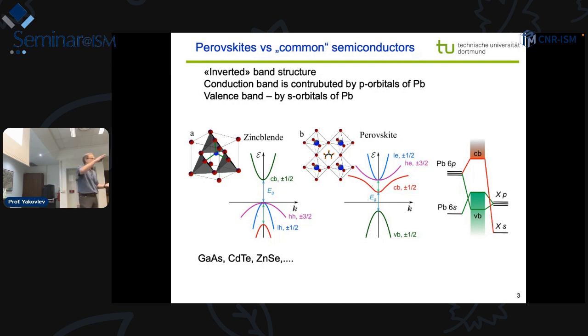You can split them in quantum wells, you cannot split them in quantum wells. And spin relaxation is fast, and many processes are limited by this. Also, if we wanted to make a full optical orientation of the spins with circularly polarized light, I will talk about this more in detail. In this complex structure, you cannot reach 100% circular polarization, optical orientation, by the excitation.